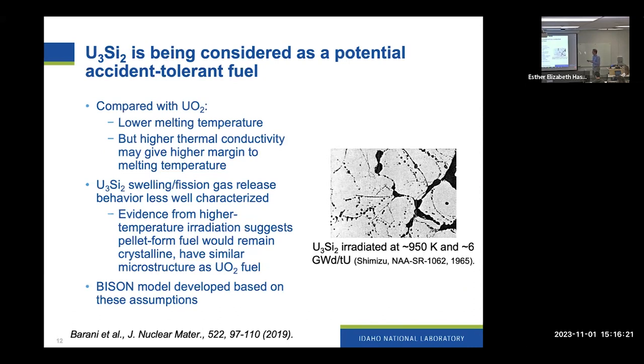As I said, UO2 is the principal fuel that's been used in most commercial reactors, but there's been a lot of interest recently in using uranium silicide as an alternative. Relative to UO2, it does have a lower melting temperature, but its thermal conductivity is also significantly greater. That can give it a higher margin to melting in the event of an accident type scenario.